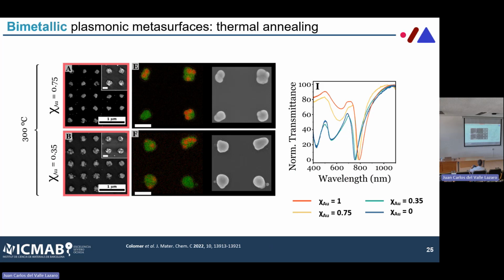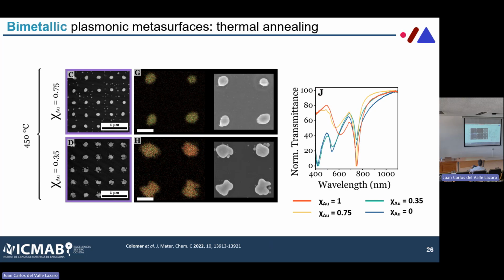We also tried to push the system to the limit, in this case by increasing the temperature. What happened is that we have complete alloying of the system. So this is a bimetallic, and the two elements are equally distributed within the structure. Once again, we observed that we could get quite sharp resonances. These are not as high as the one before, probably due to the fact that here the particles were bigger. We think that maybe using smaller particles, we can actually make the system better.